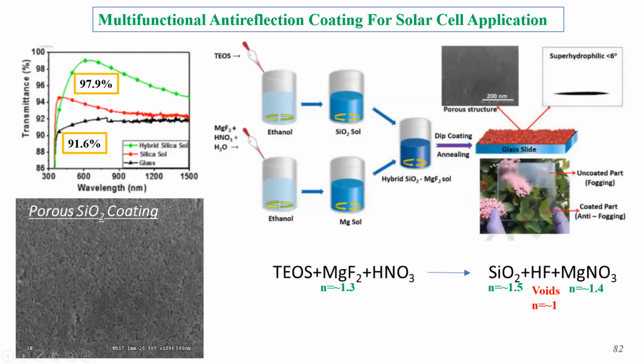So for that we can generate some different. So this coating that I have made is a hydrophilic anti-reflection coating. Whatever water we put on the coating goes inside the material. Because of this hydrophilic property, it also has an anti-fogging nature. If we put this material in the fridge, or the temperature is very cold, fogging of the material will not happen, and the transmission of light will be good even in any atmosphere.